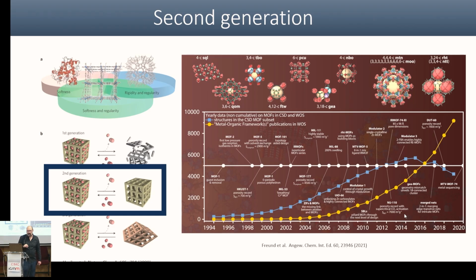In the second generation, the lattice get stable, it's rigid, okay? So once we can put in or out one gas, that can be nitrogen, can be oxygen, can be hydrogen, can be organic molecules of different size, can be drugs, can be whatever we can put inside. The porosity, as I told you, we can vary. We can make it super small, we can make it bigger, so it gets access to really very different species. And it can be single atom or multimetallics. Single atoms are a bit more weak, but not always. And then multimetallics that come around here.